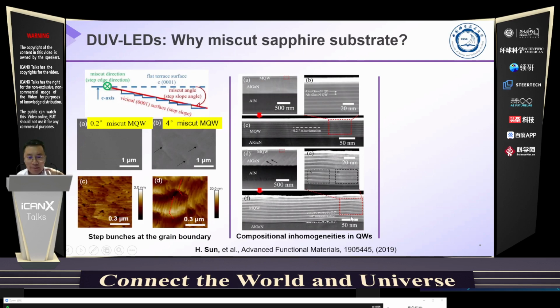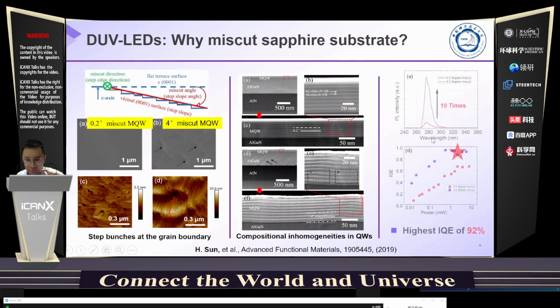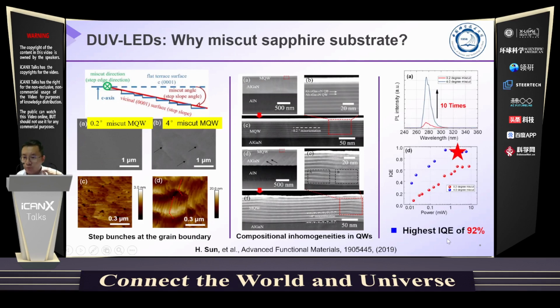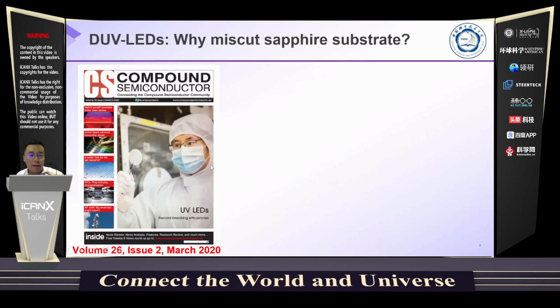The miscut sapphire substrate will lead to a fluctuation, generating a wavy quantum well, as you see here. This naturally creates a compositional inhomogeneity and leads to highly localized carrier centers. What this leads to is a significant boost of the luminescence, and we create one of the highest internal quantum efficiencies in the world.